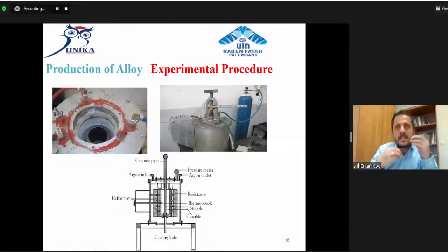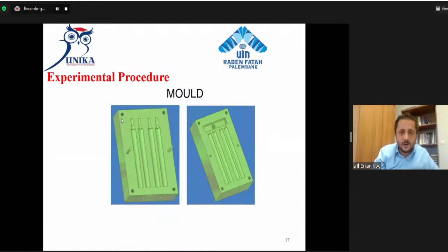You know, zinc melting temperature is lower, about 419 degrees Celsius. Our melting temperature here is 750 degrees Celsius. That's why, if we add zinc at the beginning of the melting, zinc vaporization occurs, so we have to add it 1 minute before casting. Okay, and our mold is here, 20 millimeter diameter and 200 millimeter length.